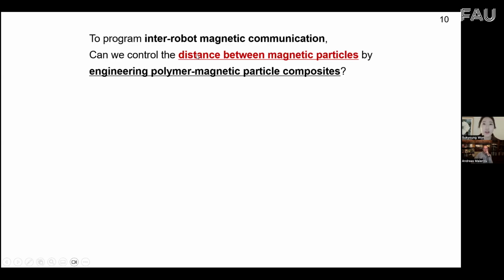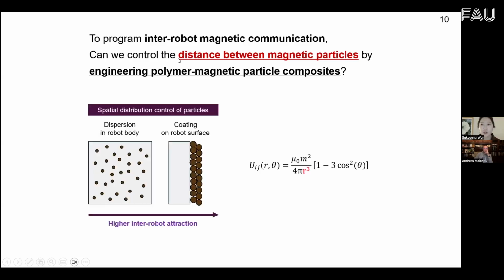This enhances the inter-robot magnetic communication, enabling more precision and some controls. One possible approach is to modify the spatial distribution of the magnetic particles. For example, we can adjust the particle dispersion inside the robot body or apply a polymer coating, particle coating onto the robot surface. According to this magnetic interactive energy equation, this decrease in the particle distance drastically increases the magnetic